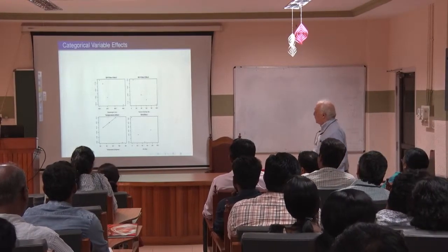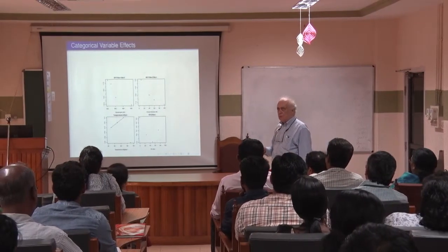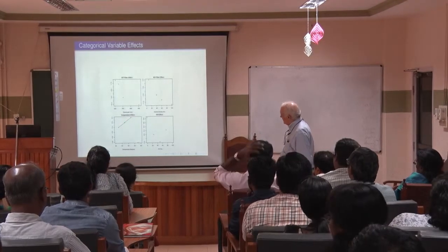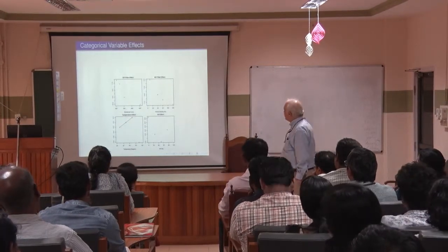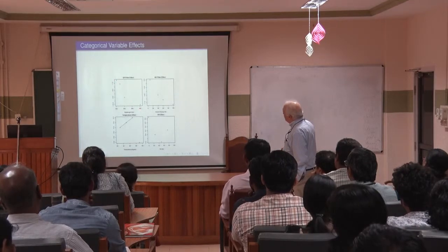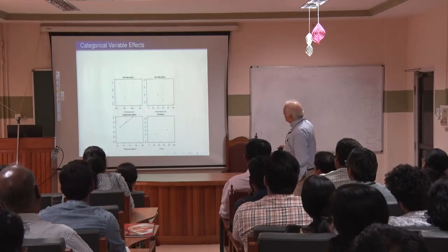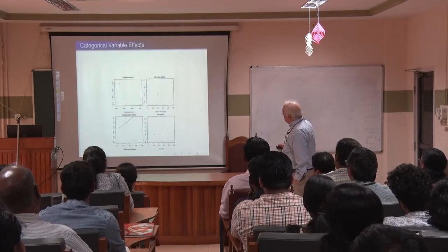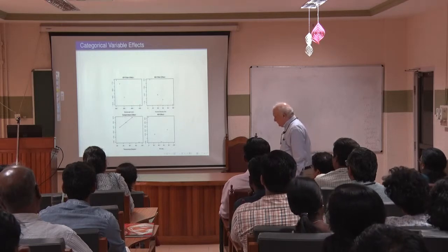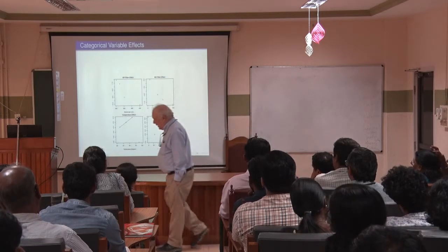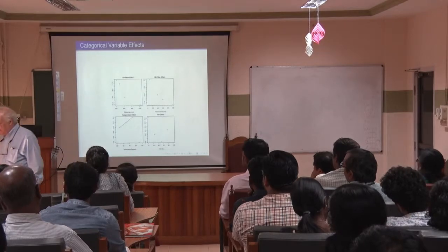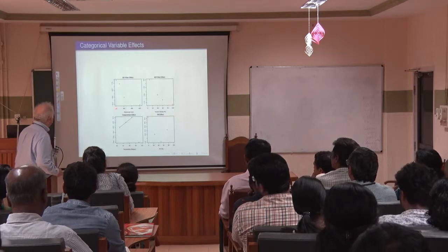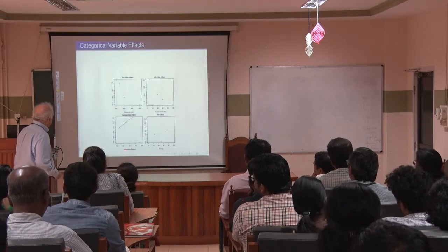And here's kind of the results that we got from our categorical model. So here's the temperature effect. It's nice and linear. So that's a nice simple one. We've got a bandpass filter effect here, which is not far from linear. And in effect, what we're doing there is looking at the effect of wavelength. Looking at the effective wavelength. There it is right there. There's the wavelength. There's the temperature wavelength.